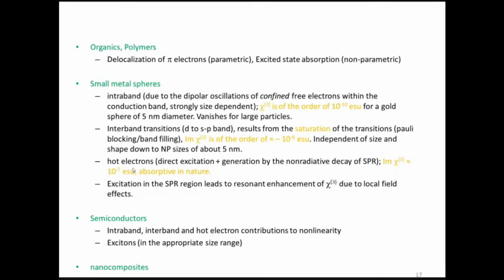And then there are what we call hot electrons. These hot electrons can be generated in metal nanoparticles by the application of very intense optical fields, and they can also be generated by the non-radiative decay of the surface plasmon resonances. So the corresponding chi3 will be about 10 to the power minus 7 ESU, one order higher than the interband transitions. Then surface plasmon resonances are very unique for metal nanoparticles. These are the collective oscillation of the electrons on the surface of the nanoparticle, and they can also contribute to the optical nonlinearity of the nanoparticle.